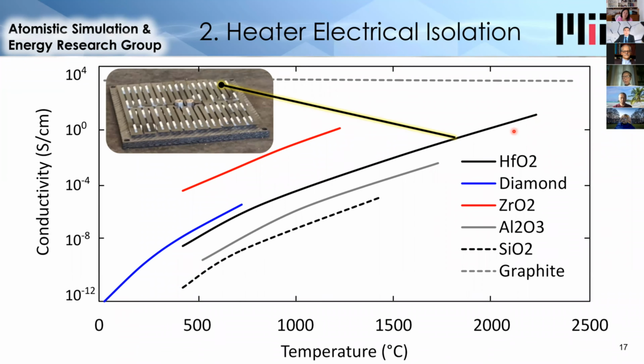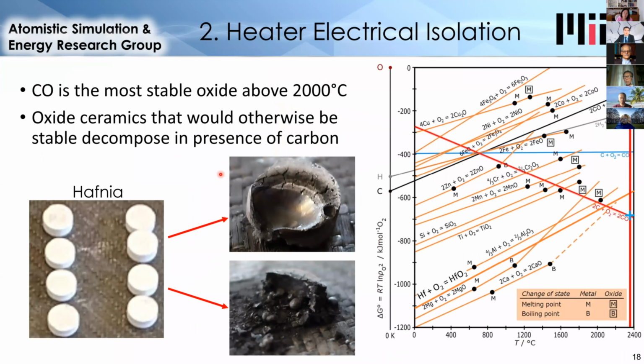And so we tried using this to separate the heater from the electrically conductive materials around it. However, in this experiment, these hafnia discs actually melted. Or they appeared to melt, but what happened was that because of the presence of carbon, both the surface the hafnia was resting on and also carbon vapor that evaporated from the high temperature heater and insulation surrounding it, the carbon oxide that can form is more stable than the hafnium oxide. And so at these temperatures, the hafnia ceramic was reduced to a metal, which has a lower melting point, which caused it to melt and then become conductive and cause the heater to fail.